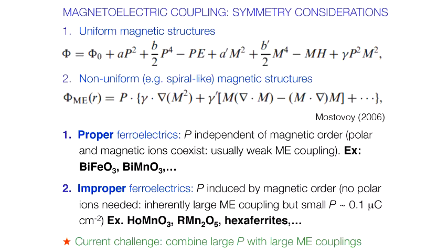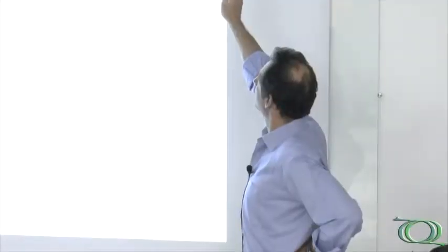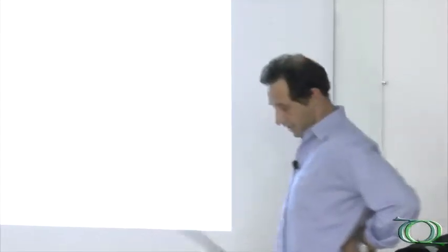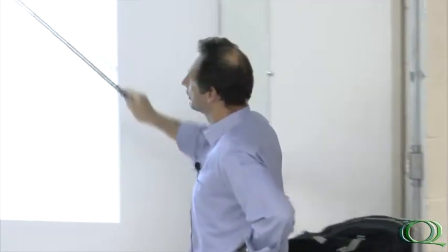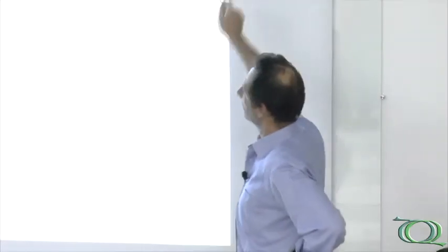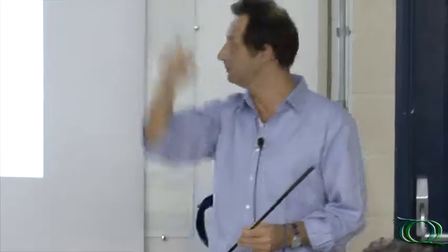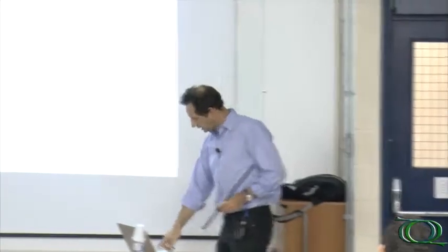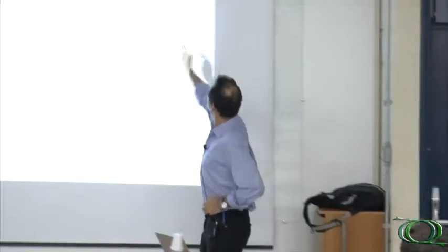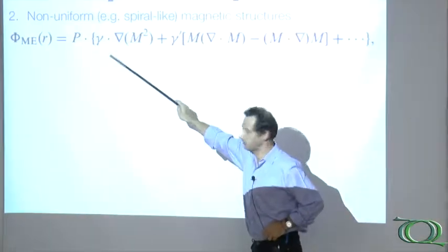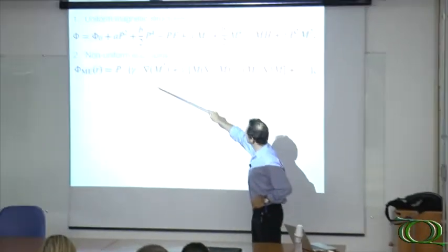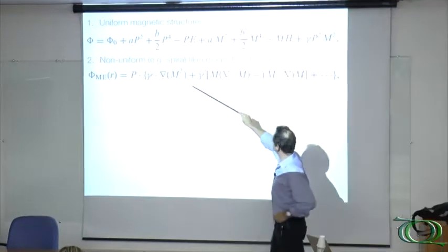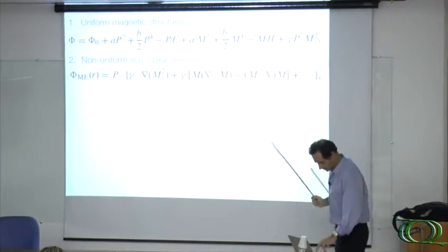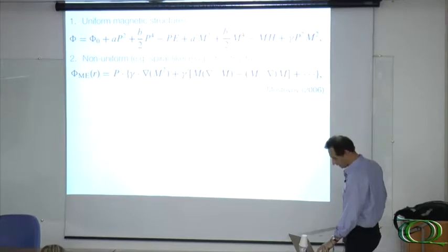And if there is, for symmetry reasons, a coupling between magnetization and polarization, the first term for a uniform magnetic structure is quadratic in both polarization and magnetization. In the case of a non-uniform, for example spiral-like, magnetic structure, it can be shown that the contribution can be linear in P, so the coupling can be larger, because then the P can couple with the gradient of the magnetization. This is a review paper by Mostovoy, which is very interesting from this aspect.